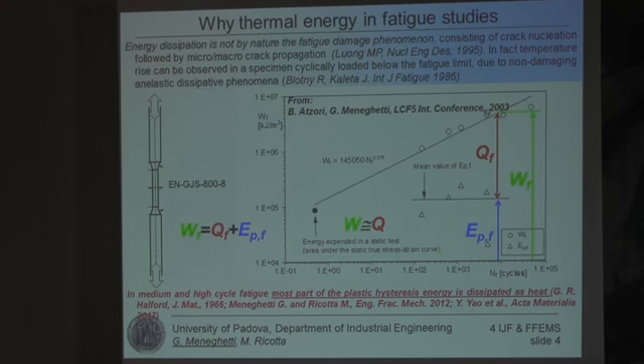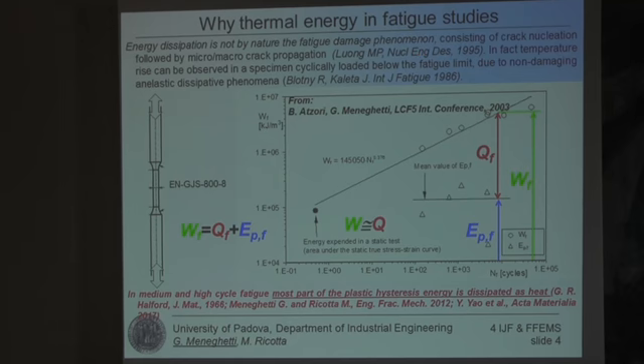Now, why should we use the thermal energy in fatigue studies? First of all, I would like to state again that energy dissipation is not by nature the fatigue damage phenomenon, as it was pointed out very clearly by Professor Luong in France more than 20 years ago, because we all know that the fatigue damage, the physical mechanism is crack nucleation followed by crack propagation. In fact, it has been demonstrated in the literature that we can measure some temperature rise of a material subjected to a fatigue test, even if the stress level is below the fatigue limit. So heat energy might be dissipated even below the fatigue limit.